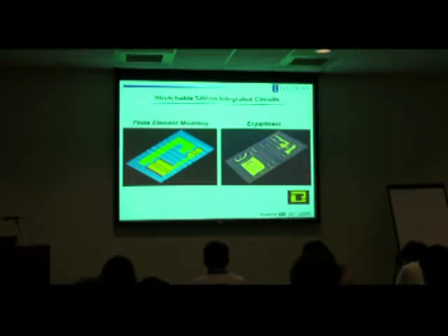And what you're seeing here is this circuit is supported on a thin sheet of polyimide like I showed you before, and then the underlying substrate is a silicone elastomer. And this is what it looks like after that buckling instability is invoked as a result of relaxing the pre-strain that's applied during the bonding step. So, again, finite element modeling and mechanics is central here. So this is an example of full 3D modeling of this particular structure.